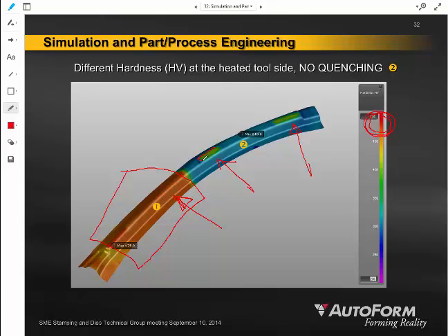And these areas where I had my pads were a little bit lower in the overall hardness scale, but still significantly harder and stronger than the areas next to them, which are in these blue or aquamarine shades. So it's very important to validate our assumptions in the manufacturing and product design process. And the way that we're doing that these days is through metal forming simulation.